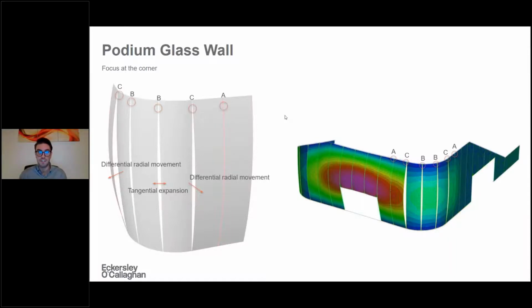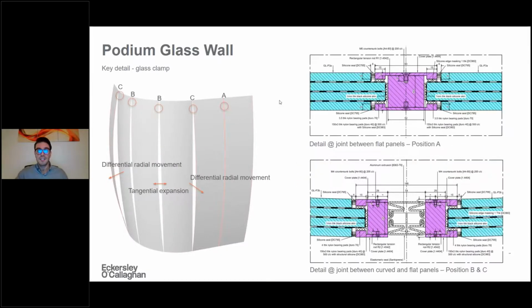A slightly different interface is what we identified as interface C, between flat and curved panel, where because of the two different stiffnesses of the flat and the curved panel, the two panels will experience not only a differential direction of movement, but also clearly the flat panel being less stiff will tend to deflect much more than the curved panel. So we have to cope with some differential radial movement between the two adjacent panels. The way we thought to address this